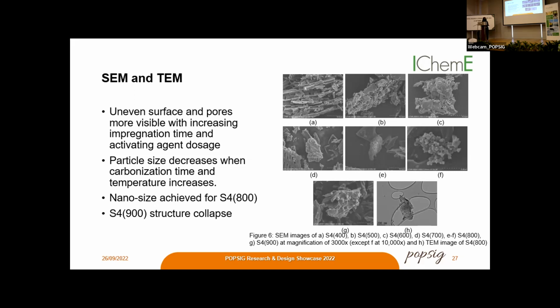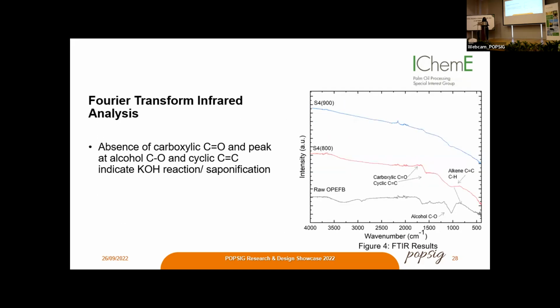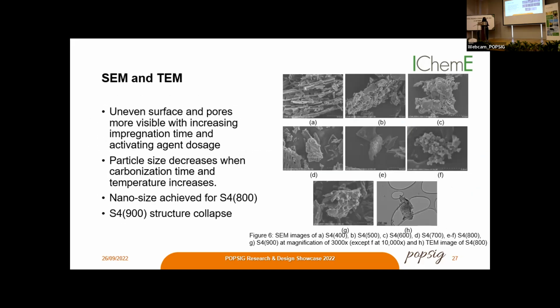On the other hand, carbonization time and temperature affects the particle size, whereby the increase in carbonization time and temperature decreases the particle size. So we can see from figure 6A to B, which represents the SEM results at different temperatures, an increase in temperature decreases the size of the particle. For 800 degrees carbonization temperature, as shown in the TEM image here, it was able to achieve nano size.